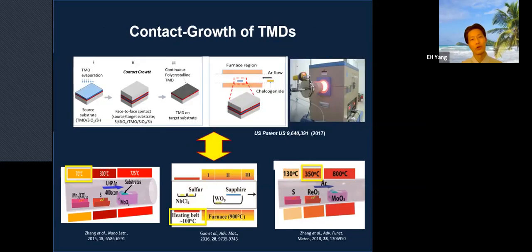We realized that our patented technology called the contact growth method is a very good fit for this iron doping. Instead of this powder approach, on the bottom you see a cartoon showing carriers with moly trioxide, dopants, and sulfur powders, and depending on where you put them, 1 centimeter more or 1 centimeter less, you get all these different results. So it is extremely difficult to control. In our case, we use a thin film. So it is much more controlled, we use a face-to-face method, and we also control the sublimation, everything. So that's what we do.